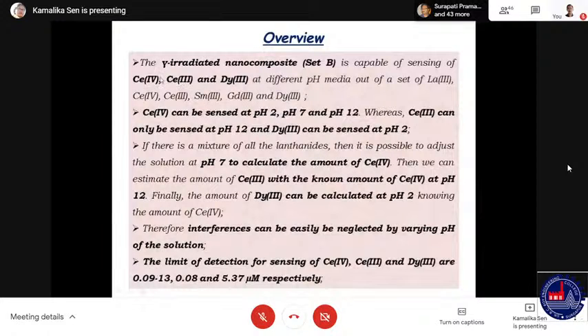The overview of this work is that gamma-irradiated nanocomposite set B is capable of sensing cerium 4, cerium 3 and dysprosium at different pH. Cerium 4 can be sensed at pH 7, 2 and 12, whereas cerium 3 can be done at 12 and dysprosium at 2.